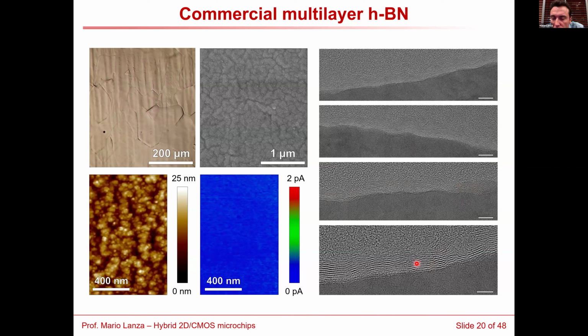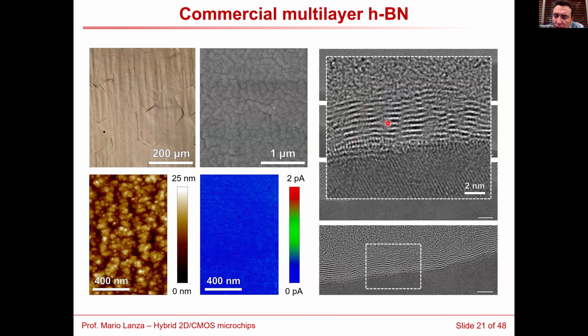Of course, there are regions where the material looks better layered, others look worse. And you can see here that almost everywhere there are a lot of local defects, and also almost everywhere you find layered locations. This is the type of material that we want for our device.